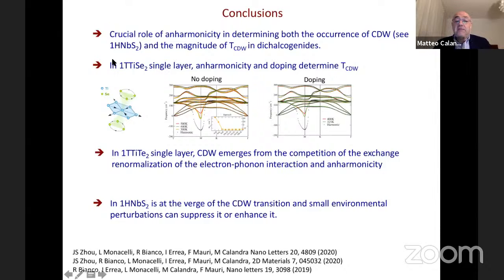So in single layer titanium diselenide, there is also an additional effect, in that the samples are actually slightly electron doped, and this quantitatively explains the occurrence of the charge density wave. So there is a combined effect of phonon anharmonicity, doping and electron-phonon interaction. And the single layer 1T titanium diselenide has always been proposed as a possible excitonic insulator. Actually, there is no need of considering an excitonic insulator to explain the occurrence of the charge density wave. In titanium ditelluride, as I told you, the explanation of the thickness dependence of the charge density wave is entirely due to anharmonicity, because at the harmonic level, you either do not explain the occurrence of the instability in both bulk and single layer, or you get instability in both.